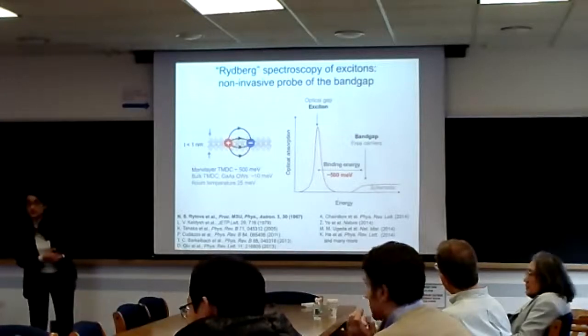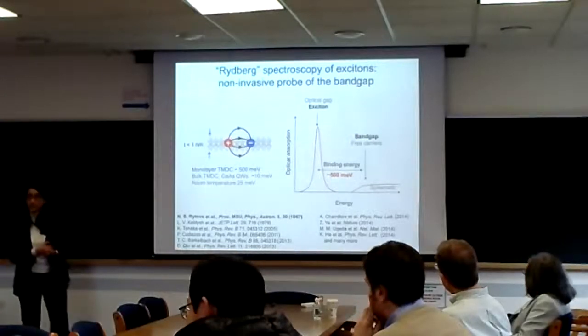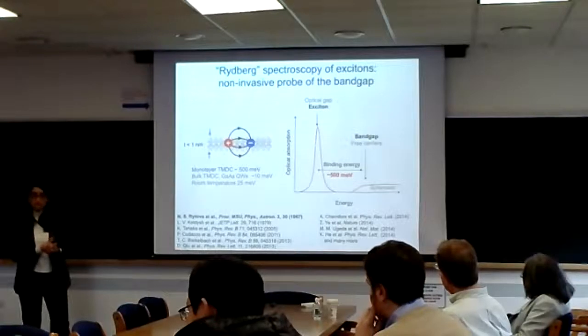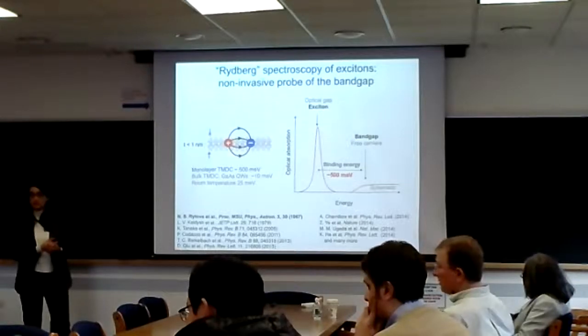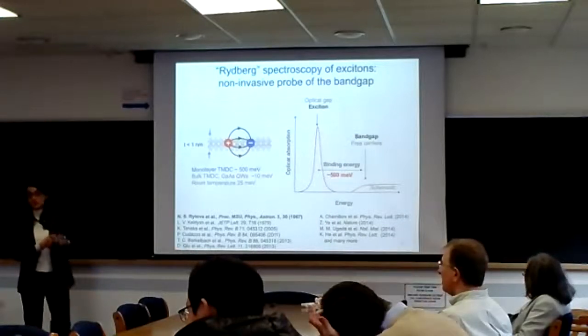And the gap width is what? I'm sorry? The gap width. Gap is 2.4 eV. So do I understand you correctly that the exciton binding energy is about 1/4 of the gap width? Yeah. The gap, and you still think that the effective mass approximation would work? No, so it's not a...